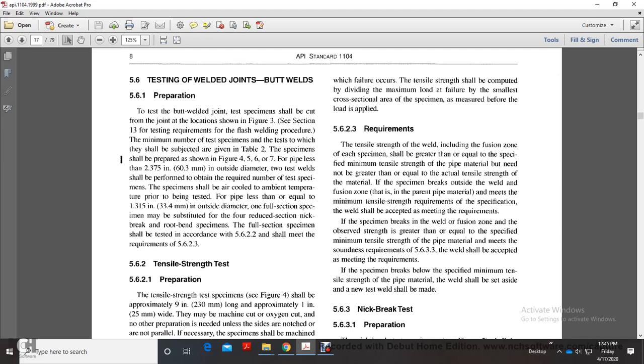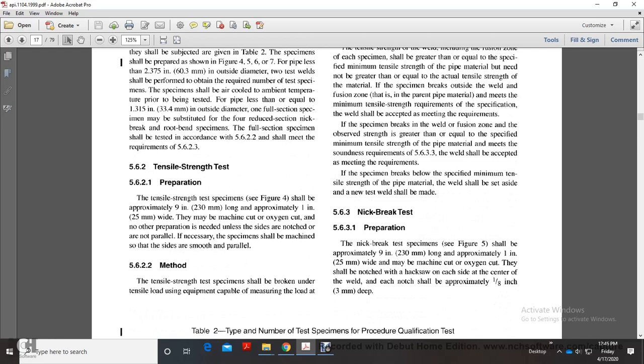5.6.2.3 Requirements. The tensile strength of the weld, including the fusion zone, of each specimen shall be greater than or equal to the specified minimum tensile strength of the pipe material, but need not be greater than or equal to the actual tensile strength of the material. If specimens break outside of the weld and fusion zone, and the parent pipe material meets the minimum tensile strength requirements of the specification, the weld shall be accepted. If the specimen breaks in the weld or fusion zone and the observed strength is greater than or equal to the specified minimum tensile strength of the pipe material, and it meets the soundness requirements of 5.6.3.3, the weld shall be accepted. If the specimen is below the specified minimum tensile strength of the pipe material, the weld shall be set aside and a new test weld shall be made.